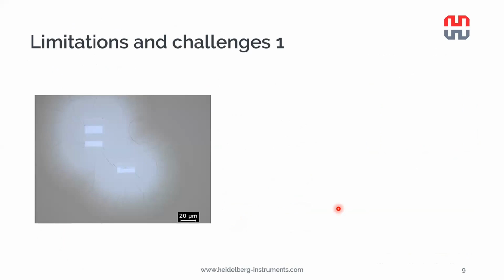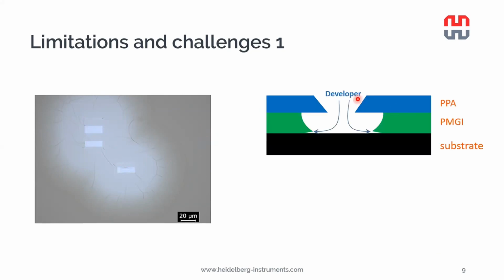So what can be the limitations and challenges when we carry out a bilayer lift-off? First of all, when we were starting to develop this process, we quite often observed this kind of halo image around our structures. So here we want to transfer these bright squares into the metal. What this turned out to be is that the developer is water-based, while PMGI is quite strongly hydrophobic material, and the substrate was untreated silicon, so the native oxide was hydrophilic. And as a matter of fact, the developer wanted to penetrate between the PMGI and the substrate and push away to lift off the resist material. This is what we can see here.